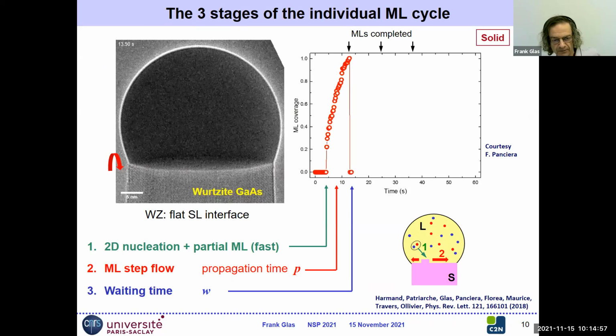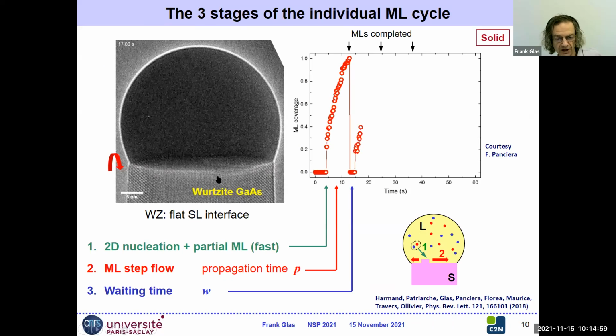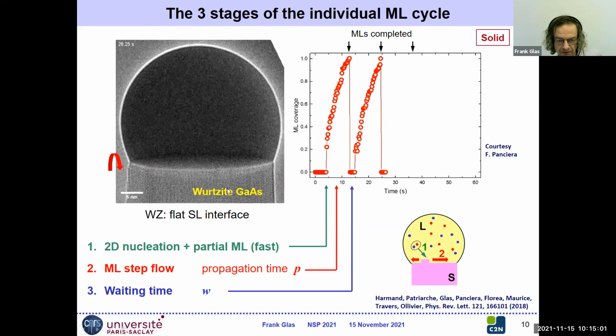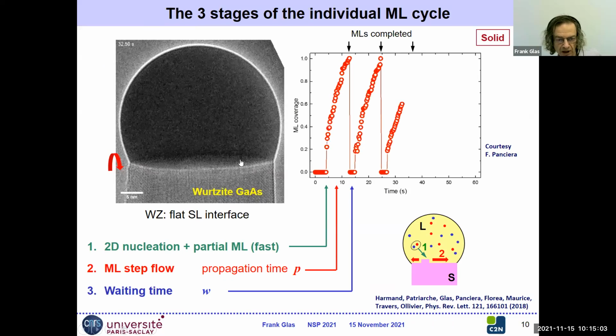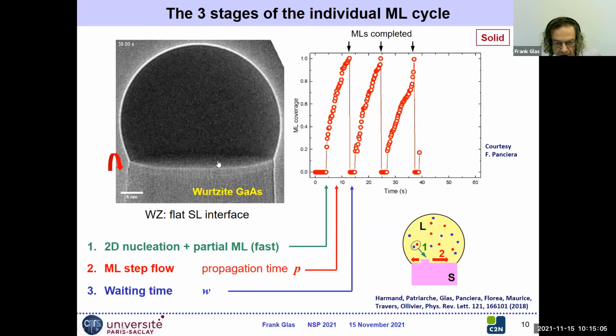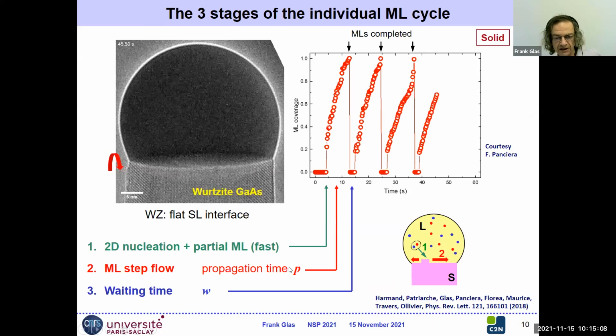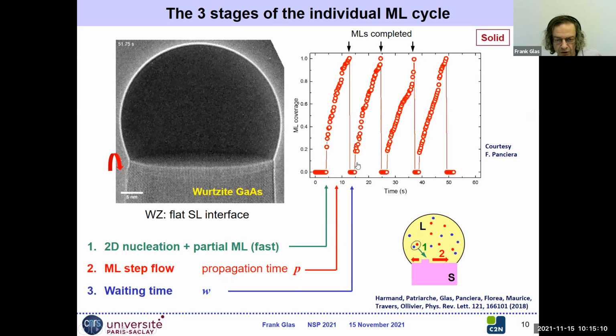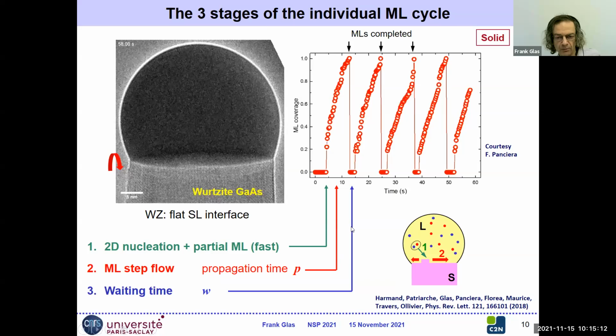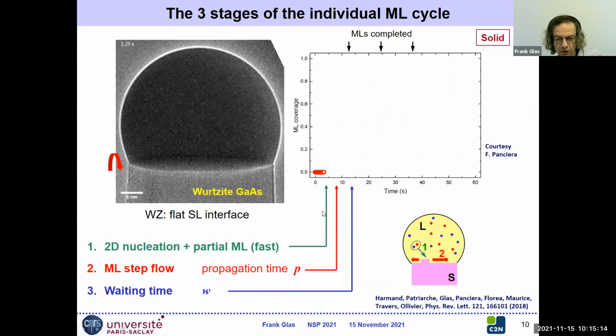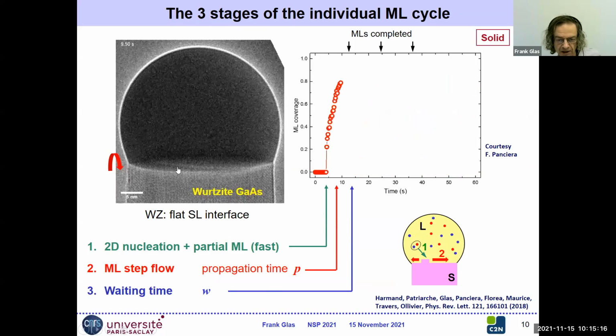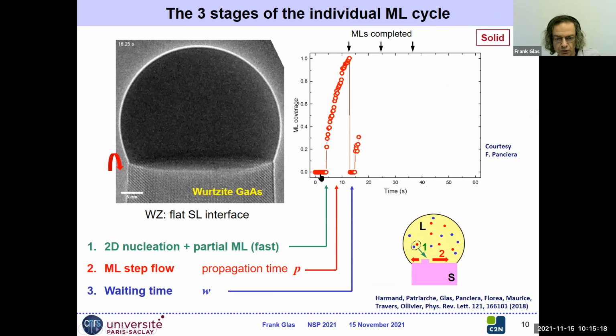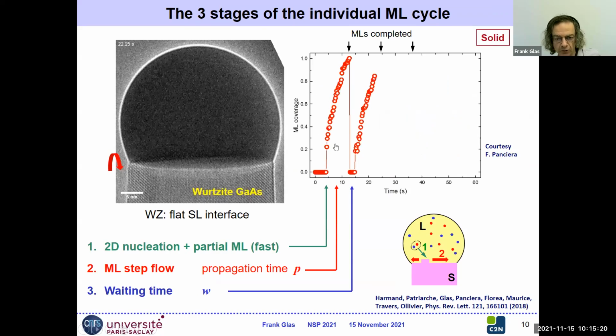So here is a video from Federico Panciera. Again, we have a tilted interface, wurtzite gallium arsenide nanowire. You see maybe a bit more clearly the monolayers forming and propagating at the interface. And on the right here, we have plotted the variation with time of the coverage of the interface by the monolayer. So the coverage varies between 0 and 1.